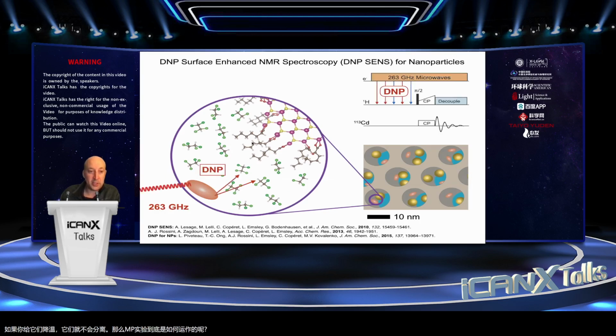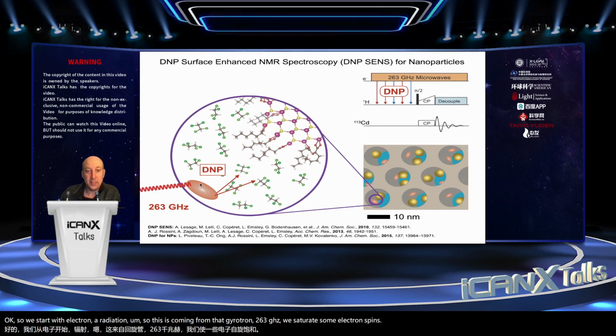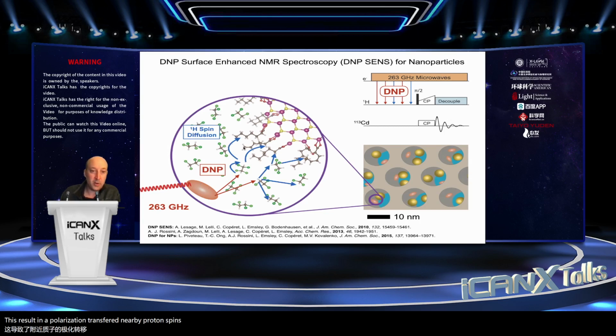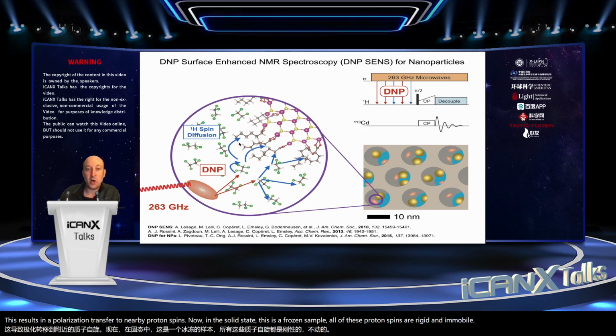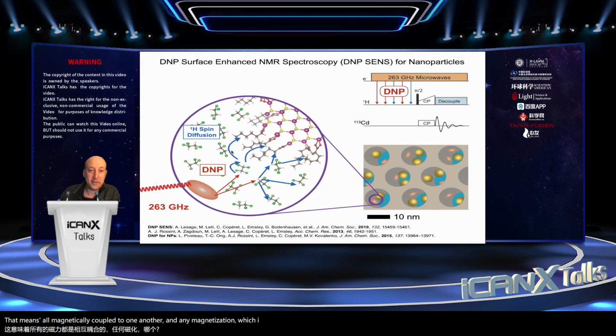Okay, so we start with electron irradiation. So this is coming from that gyrotron, 263 gigahertz. We saturate some electron spins. This results in a polarization transfer to nearby proton spins. Now, in the solid state, this is a frozen sample. All of these proton spins are rigid and immobile. That means they're all magnetically coupled to one another. And any magnetization which I get off the electron spin initially will be transferred to nearby proton spins, and it will kind of diffuse throughout the sample. We call this proton spin diffusion.